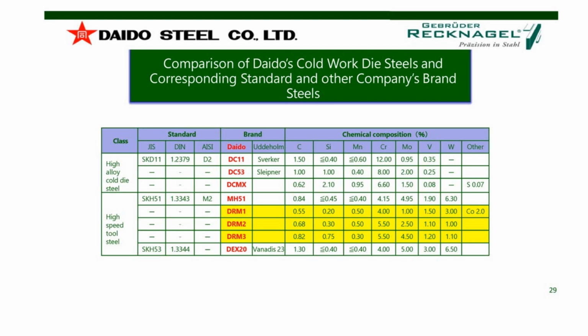You can see the DRM1, DRM2, and DRM3 with the yellow marking. And over there, you can see the M2 grade. The big difference, or the most important, is of course the carbon content. M2 has about 0.84% carbon. Dream 1 is very limited, up to 0.5. Dream 2, about 0.7. And DRM3 has, I guess, the same carbon content as the M2 grade.